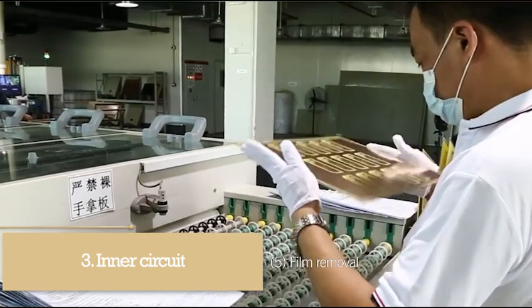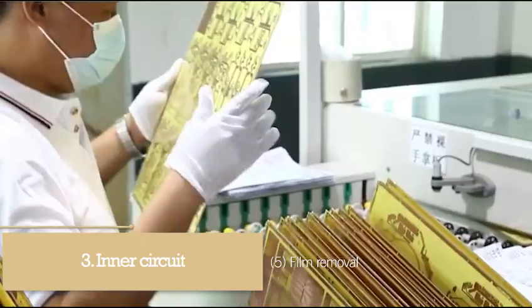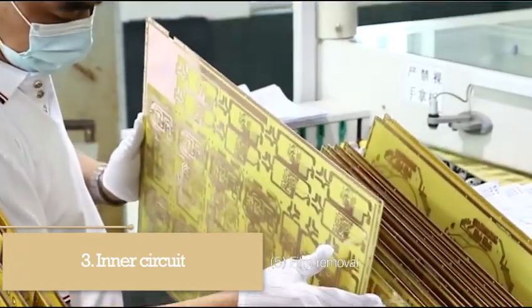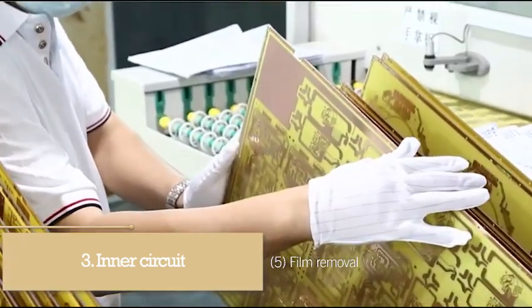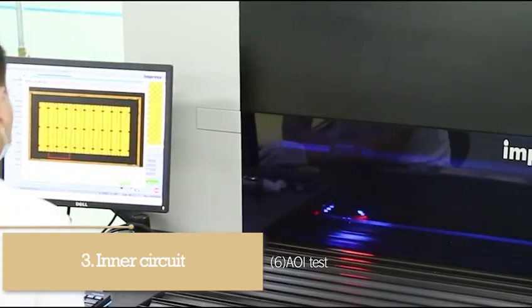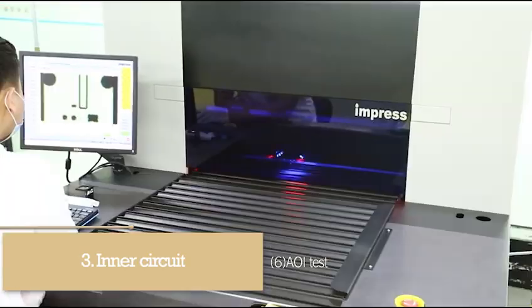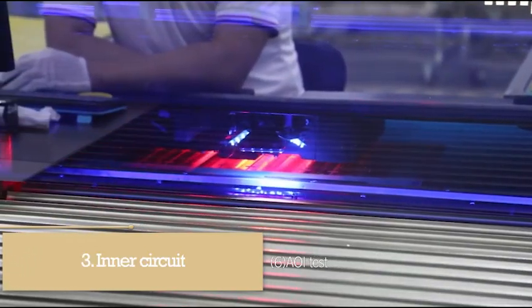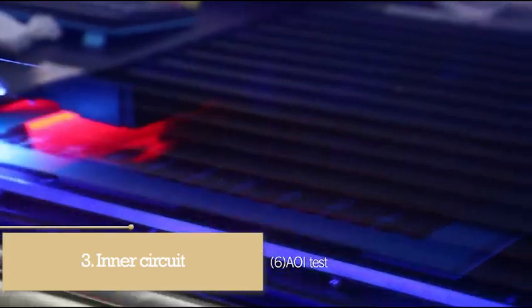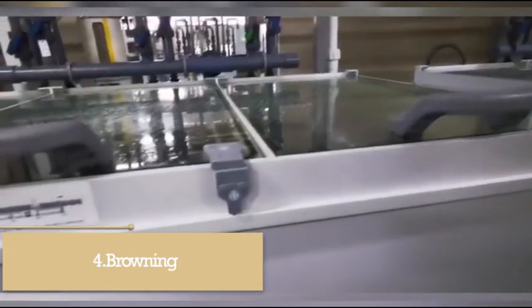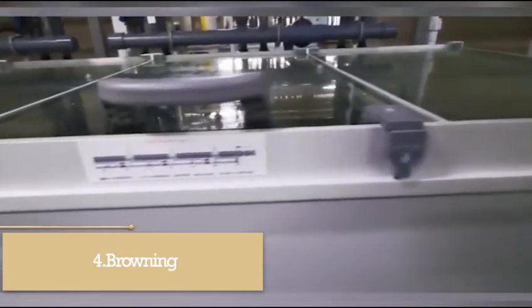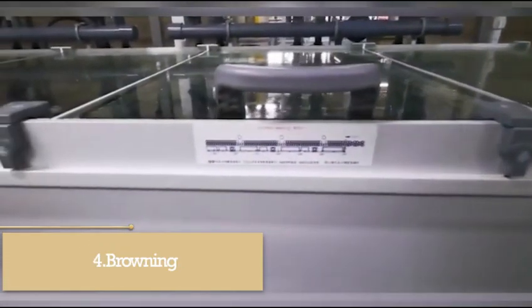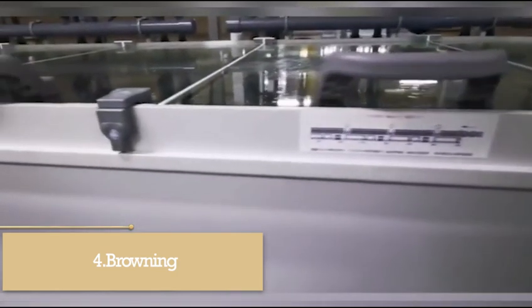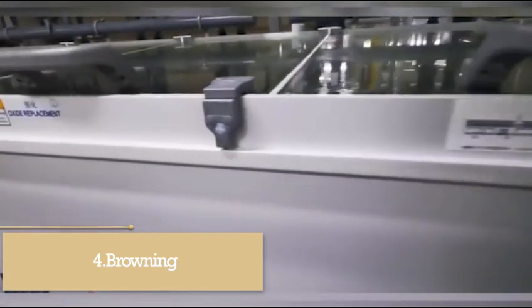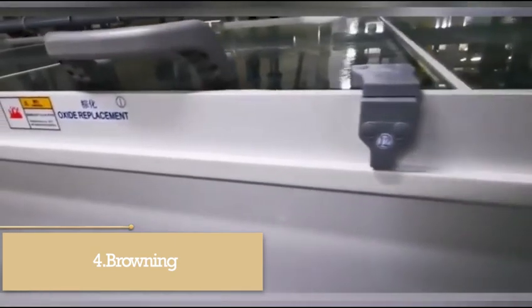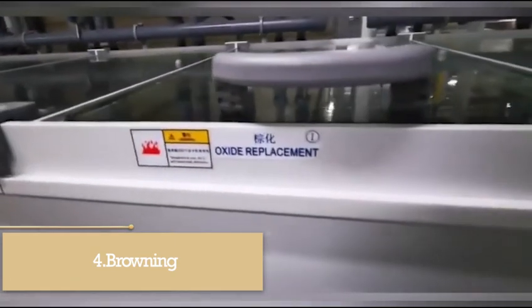Use sodium hydroxide solution to peel off the exposed dry film, protecting the copper surface to expose the circuit pattern. 6. AOI test. Using a high-definition line array camera, the PCB surface graphics are extracted and compared to detect line defects. 4. Browning. Through chemical treatment, a uniform organic metal layer structure with good adhesion properties is produced, which is used to enhance the adhesion strength between the inner layer and the prepreg after pressing.